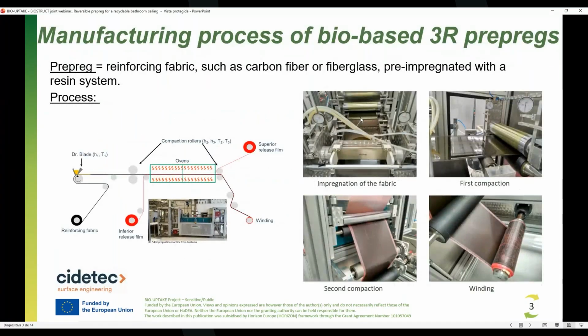So a prepreg is composed of a reinforcing fabric, usually carbon fiber or glass fiber, which is pre-impregnated with a resin system. In the fabrication process, the fabric goes through a doctor blade where it's impregnated, and then it enters the first compaction roll. When it comes out, together with the inferior release film, it continues through the ovens where a temperature can be applied, to the second compaction roll. Here the superior release film is also added, and finally we wind the material to obtain a